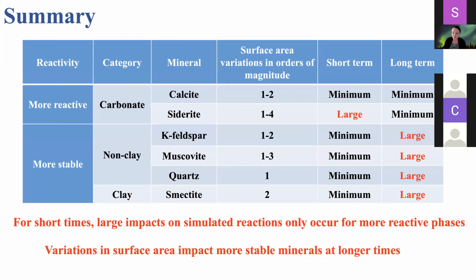So to summarize what we found from this investigation, it really depends on what kind of phases you have in your system, as well as the time scale that you're interested in. If you're interested in what's happening at this laboratory time scale, the short time scale, we really saw variations in the most reactive phases, which were the carbonate phases here. But if you want to know what's going to happen at the longer time scale, it doesn't really matter what the surface area value was that you're using for the carbonate phases, but it did matter what was happening with these more stable phases that start reacting over longer time scales. For these phases, the surface area had little impact on what was happening at short time scales, but did have some large variations as you're approaching the several years time.